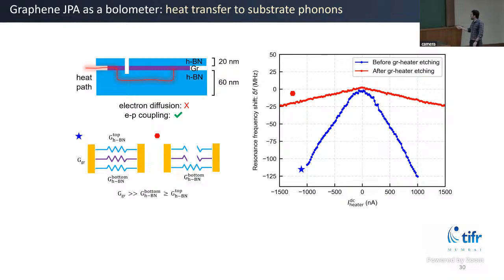Now when you etch the graphene, you are eliminating this channel. So now you are left with the substrate phonon. If there were no heat conduction through this phonon path, this line would have been flat, with no frequency shift. But we do see a finite frequency shift when the graphene is etched, which indicates the heat is going through the substrate phonon.